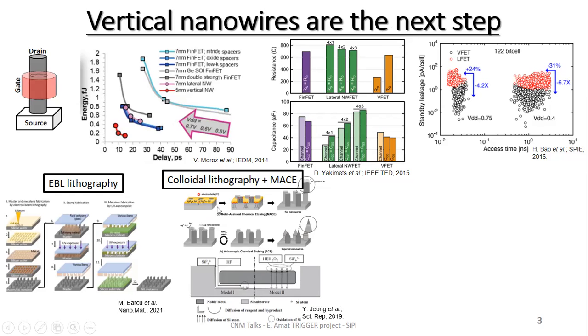of the metal layer. Usually, it is implemented using gold or silver, and then using a specific solution made of peroxide and fluoridic acid. You oxidize the region below the metal, and then with the HF, the fluoridic acid, you remove this oxide layer, and then the metal layer goes down, and the pillars arise.